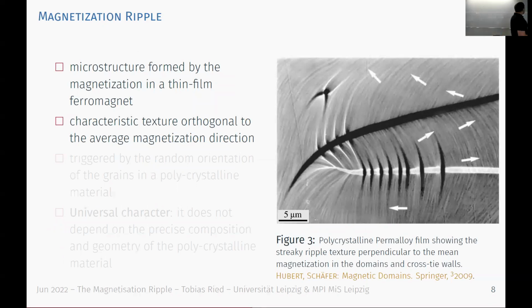First of all, it is a microstructure formed in thin film ferromagnets, and let me show you another picture. It somehow has this nice property that it's always an oscillation orthogonal to the average magnetization direction. So in such pictures, you can actually read off the main magnetization direction by looking at these fine oscillations, and the main magnetization direction is orthogonal to these oscillations.